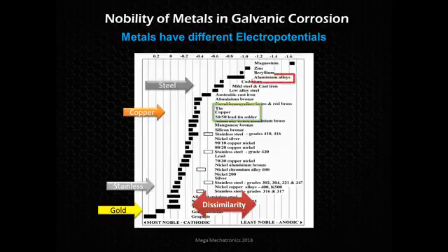So they're not going to eat each other up. On the other hand, we have aluminum alloys really high up there. And if you combine the aluminum with, let's say, a stainless steel near the bottom, you're going to have trouble where that aluminum is going to start degrading. And same with copper. When you connect aluminum to copper, you need to seal it off, use some zinc paste. So you see that zinc is less noble, and the zinc will actually sacrifice itself.